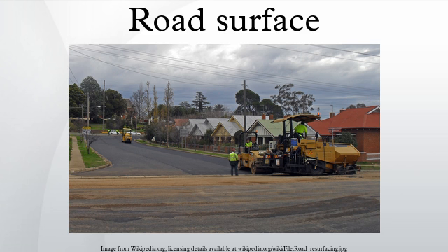To decrease reflective cracking, concrete pavement is broken apart through a break and seat, crack and seat, or rubblization process. With break and seat and crack and seat processes, a heavy weight is dropped on the concrete to induce cracking, then a heavy roller is used to seat the resultant pieces into the subbase. The main difference between the two processes is the equipment used to break the concrete pavement and the size of the resulting pieces. The theory is frequent small cracks will spread thermal stress over a wider area than infrequent large joints, reducing the stress on the overlying asphalt pavement.